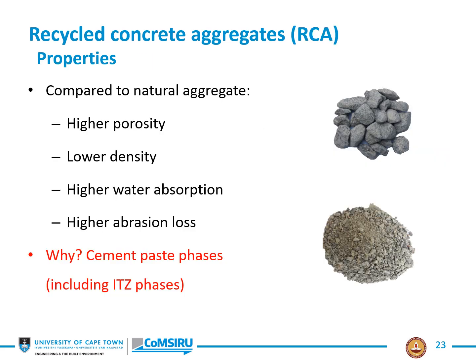And so if we compare recycled concrete aggregate with natural aggregate, we find that it has higher porosity. That's due to the adhered mortar, lower density, higher water absorption, and higher abrasion loss. And as I've said, all due largely to the cement paste phases, including the ITZ phases.